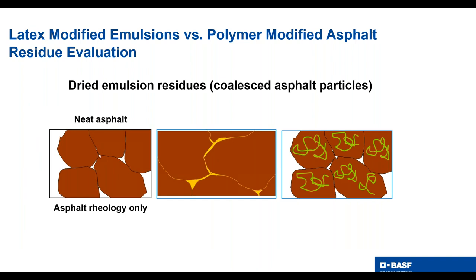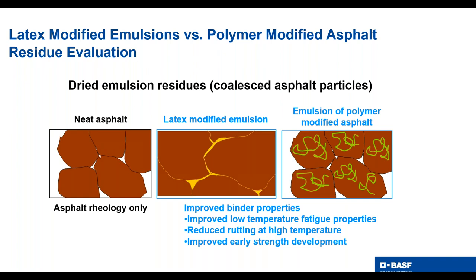The picture on the left is neat asphalt, so you just have asphalt without any polymer. The picture in the middle is latex modified emulsion. Those latex droplets will cure and break, and you'll see them form kind of a film around the asphalt droplet. And this is very important when we look at it. But if you have a polymer modified asphalt, those droplets have to coalesce and blend together as themselves.